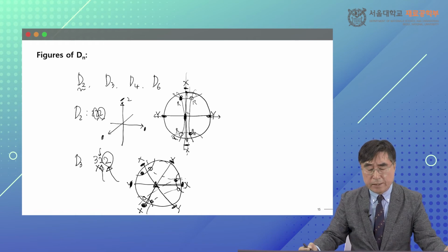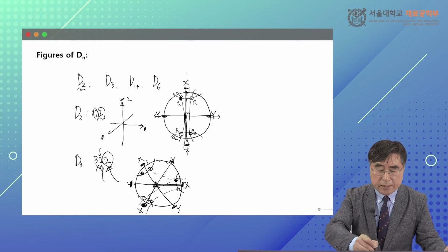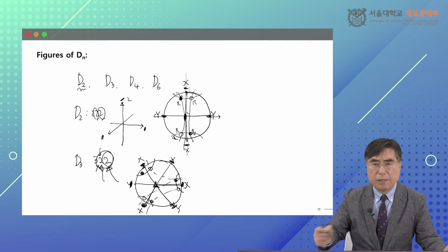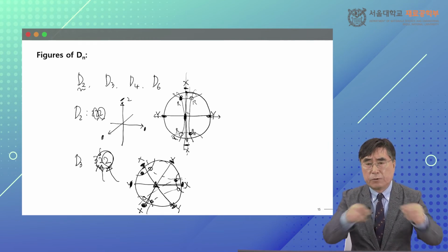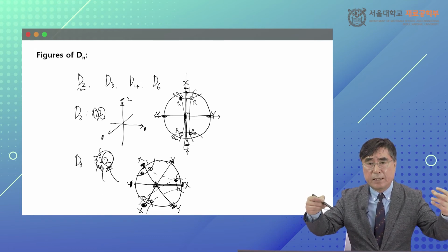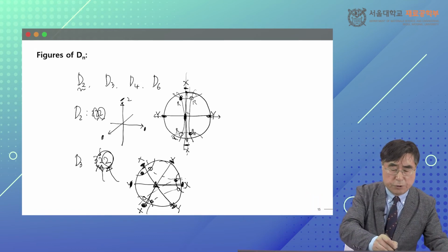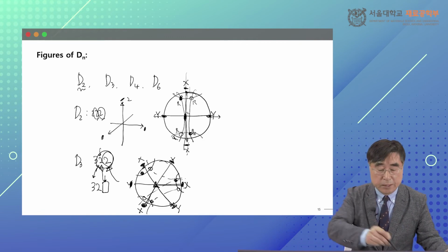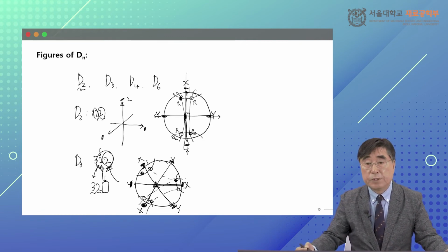In this case, you see that this x symmetry and y symmetry, which look different in here, are basically the same thing. The rotation axis should penetrate. So X, Y is basically the same thing. So you don't have to write down 3, 2, 2. So people write down 3, 2, just blank in here. That explains all the symmetry elements. So this is the international symbol of D3 as 3, 2, instead of writing it 3, 2, 2.